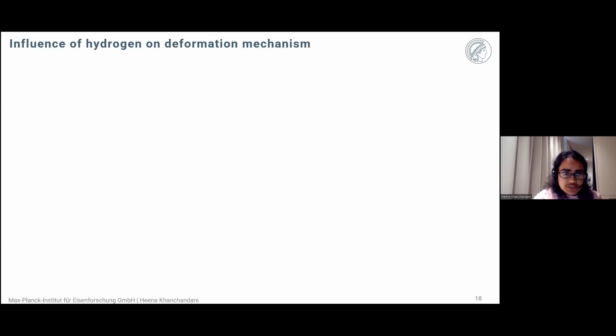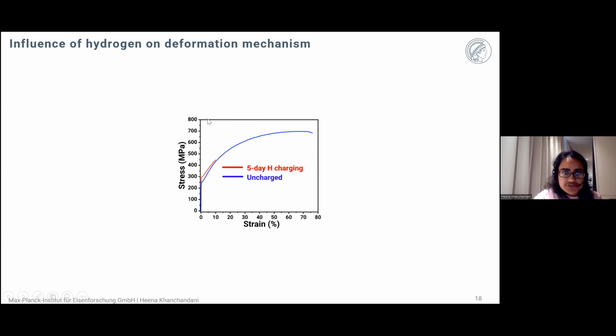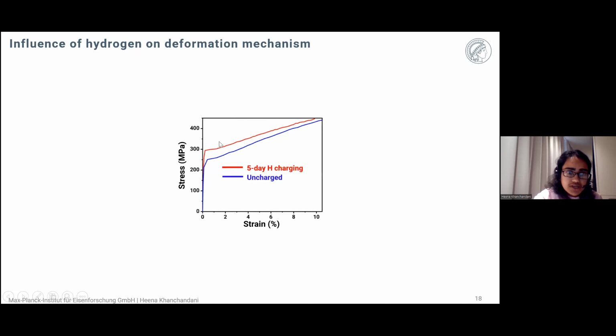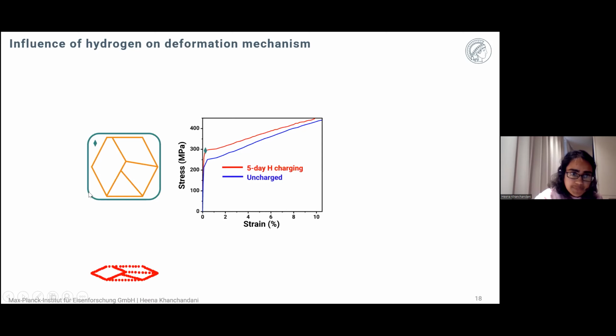So I would like to briefly explain this mechanism. Here is our stress strain curve of the charged and the uncharged samples. And now I would like to show only the region of the stress strain curve up to 10% of strain, because the hydrogen charged sample fractures at 10%. Here is the one. And here is our microstructure with grain boundaries. When we charge it with hydrogen, hydrogen is segregated at all these grain boundaries, which is why it delays the dislocation nucleation from the grain boundaries by delaying the Frank-Read source mechanism, which is why there is an increase in the yield strength after hydrogen charging.